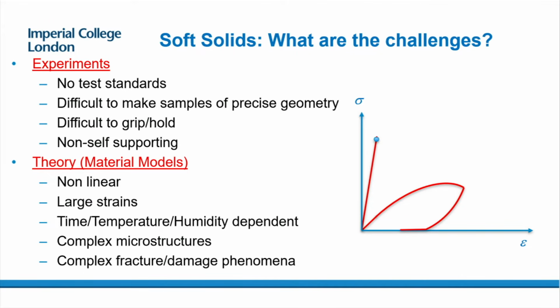This material, when you load it and unload it, it will come back the same way, which literally means that at the end of the test, you have the sample looking exactly the same as it did before you tested it. Okay? There's no damage in this sample. This material, once you load it and then you unload it, it will come back a different way, and it will stop somewhere here, and no matter how long you wait, you have this permanent deformation in the sample.